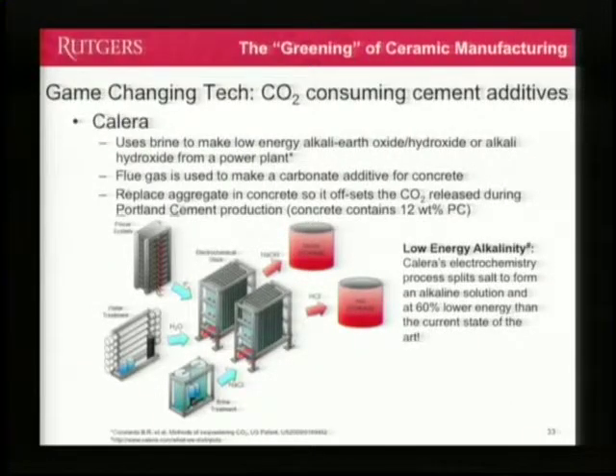But I still don't think their calculation is complete. They've placed no numbers on what the CO2 footprint is for making the alkaline earth hydroxide. They have to do this. You cannot take cations out of seawater unless you raise the pH to at least 13 or 14. And then the process of precipitating the solids lowers the pH back to 7. It's a neutralization reaction. So for every mole of material they want out as a carbonate, they're going to have one CO2 neutralized by a sodium hydroxide. So we'd like to see what that number is.